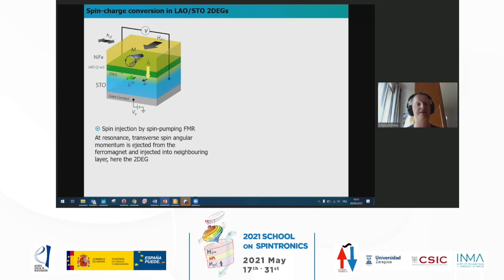So we did a spin to charge conversion experiment in our LAO STO 2DEGs in collaboration with the group of Laurent Vila in SpinTec. And to inject the spin, we use a technique called spin pumping FMR. So we have a ferromagnet, which we grow on top, and we put this sample in a microwave cavity, and we scan the magnetic field until we reach a resonance condition for the magnetization, at which point the magnetization starts to precess. And as it does precess, a finite density of spin angular momentum, that's basically spin current, is ejected from the ferromagnet and injected into the 2DEG, where we expect it to be converted into a 2D charge current by the inverse Edelstein effect.